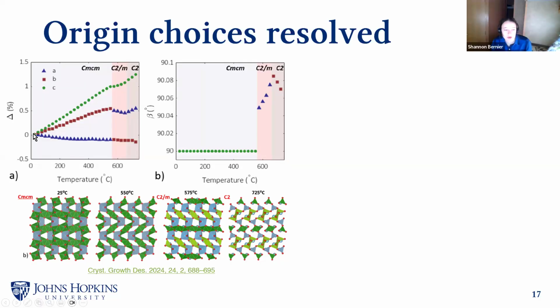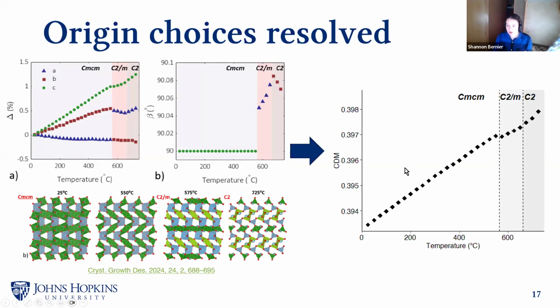Well, I'll continue. So this crystallographic redefinition is not critical. And so one of the things that our CDM accomplishes is it takes into account that swap. It's agnostic to the choice of origin. And so we no longer have to deal with that confusion. It also does a really great job of showing the lattice expansion of how we're moving further and further away from a cubic lattice as we continue, which can be a little bit obscured by the fact that, for example, if you were just following this B parameter, it actually doesn't go up continuously, it goes down and up. And yet we still see discontinuous transitions at the phase transitions.